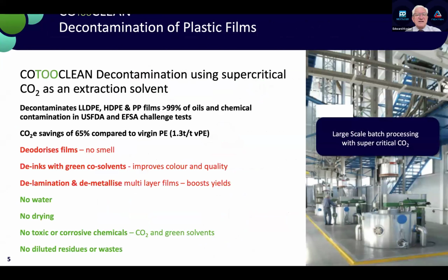The process we're working with, called CO2 Clean, is a decontamination process, and we use carbon dioxide in the supercritical phase as an extraction solvent. This is similar to other processes that use supercritical carbon dioxide as a solvent, but in this case, we have a non-toxic material. And we know that we can remove greater than 99% of any oils and chemicals that may be in contact with polyolefinic film materials.